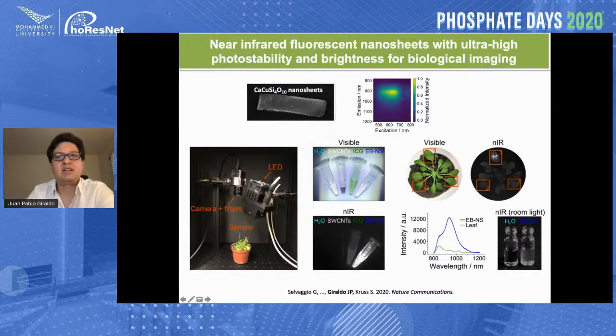As you can see in this image, these are the carbon nanotubes, and this is the silicate nanosheets. In this near infrared fluorescence image, you can see the differences in brightness with the same excitation. So this could allow for potentially simpler sensing with higher signal to noise ratio imaging with an LED, simply using a system having an LED excitation and camera, perhaps not even a near infrared camera. It could be just a normal silicon dioxide-based sensor camera.